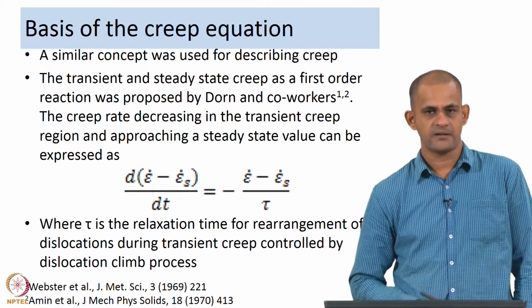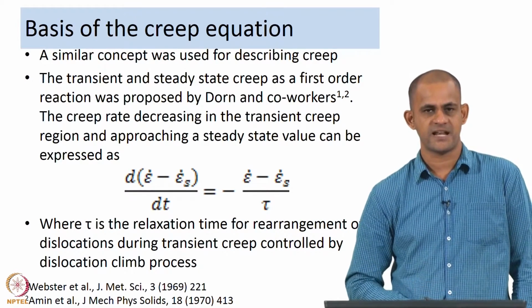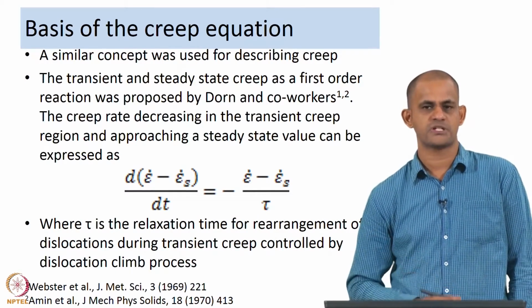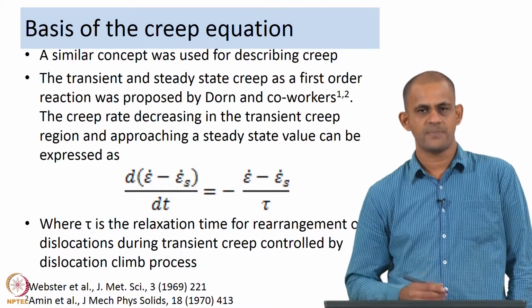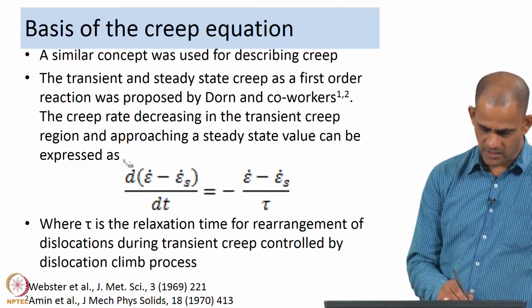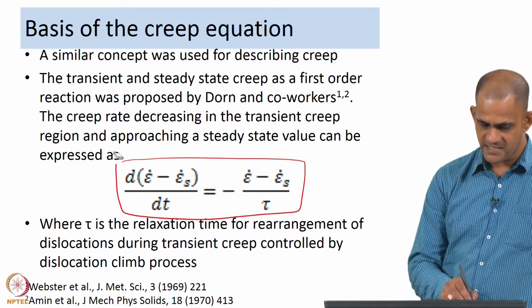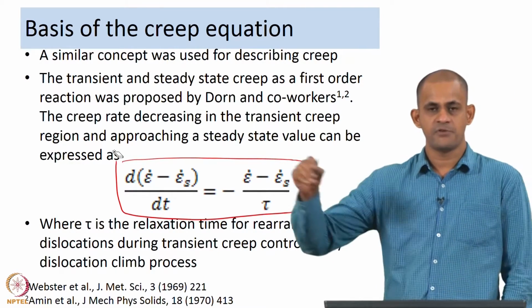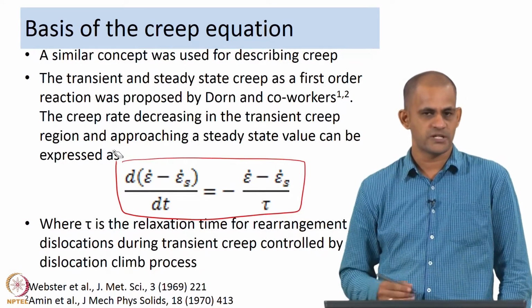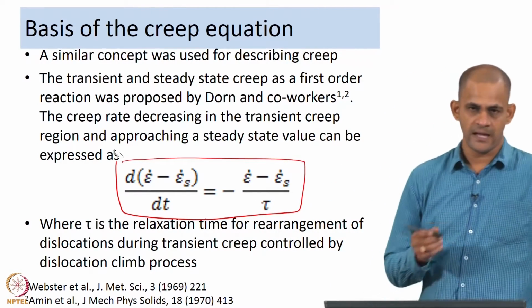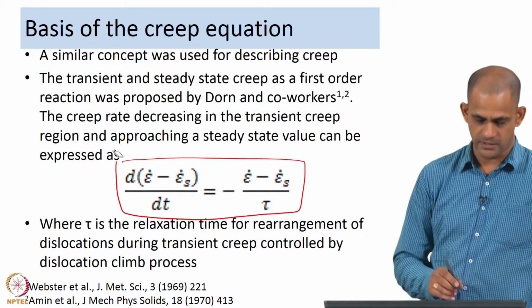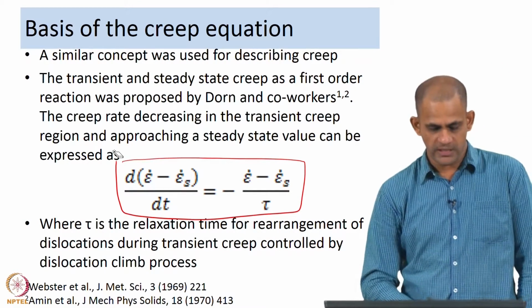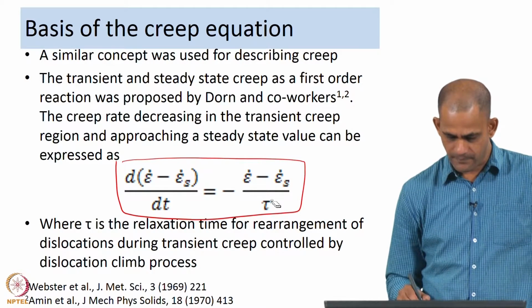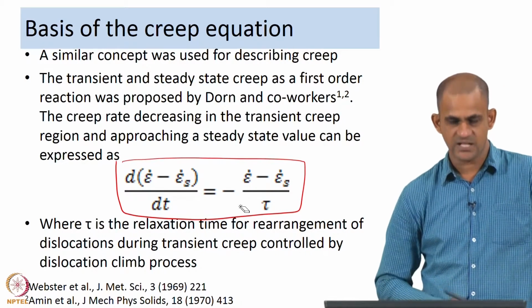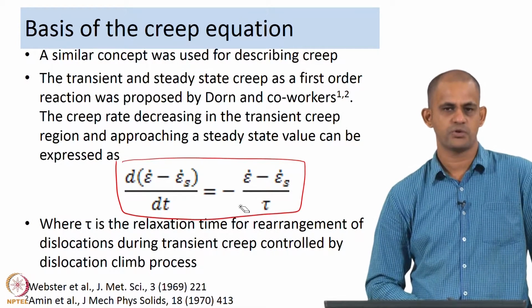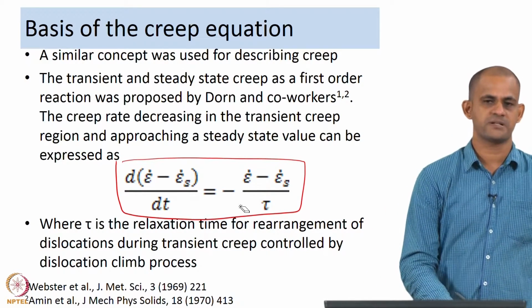The creep rate is known to be decreasing in the transient creep region and to approach a steady state value. That kind of behavior can be modeled by using an equation like this. The decreasing strain rate in primary creep eventually leading to steady state creep can be captured by the following equation. Here you have a term tau. Tau is the relaxation time for rearrangement of dislocations during transient creep controlled by the dislocation climb process.